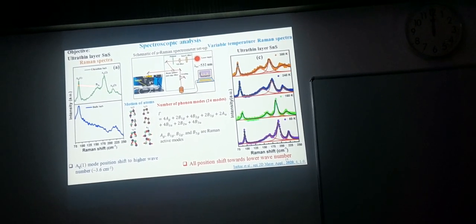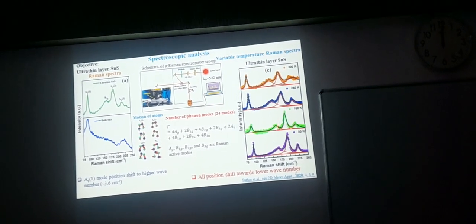It has many different vibrational modes, which are inactive or active. It depends on the modes and the laser excitation source as well. So in this case, we have four vibrational modes appearing, and we started the temperature-dependent Raman spectra to understand the thermal properties. Not only that, first the temperature coefficient, that is the phonon energy and phonon lifetime in this case.